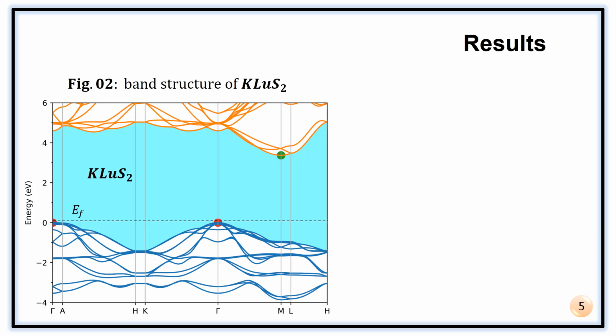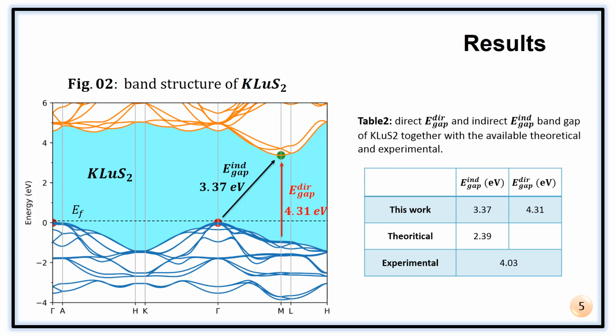In order to find out the band gap and the effective mass of the studied material, we have calculated its band structure. So based on this figure, we can conclude that this material is a semiconductor with indirect and direct band gaps of 3.37 and 4.31 electron volt respectively. If we look at the table, we will see that our results are very close to the experimental, much better than the other theoretical results available in the literature.